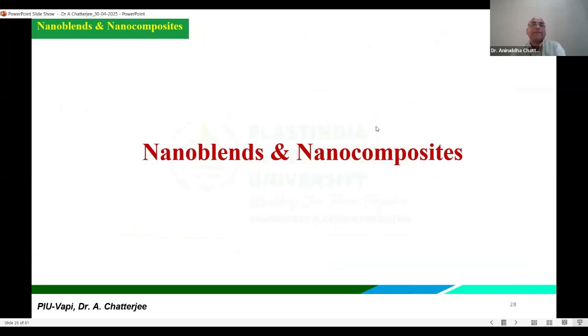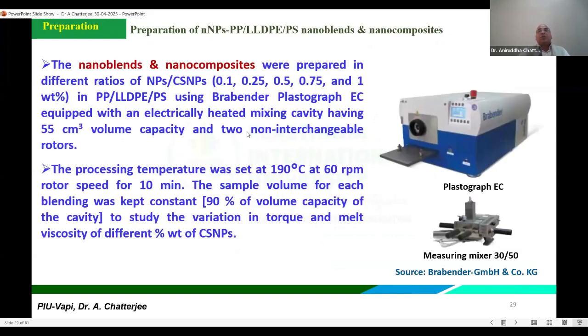So now, nano blends and nanocomposites. Whatever nanoparticles I have synthesized, like polystyrene and polymethyl methacrylate, I have incorporated in different polymeric matrices, that is polypropylene, LLDPE, and PS, using a Brabender plastograph. From 0.1% to 1% loading of nanoparticles, we have studied different properties. The process temperature was set at 190 degrees centigrade at 60 rpm rotor speed for 10 minutes. The sample volume for each blending was kept constant, 90% of the volume capacity of the cavity, to study the variation in torque and melt viscosity at different weight percentages of core shell nanoparticles.